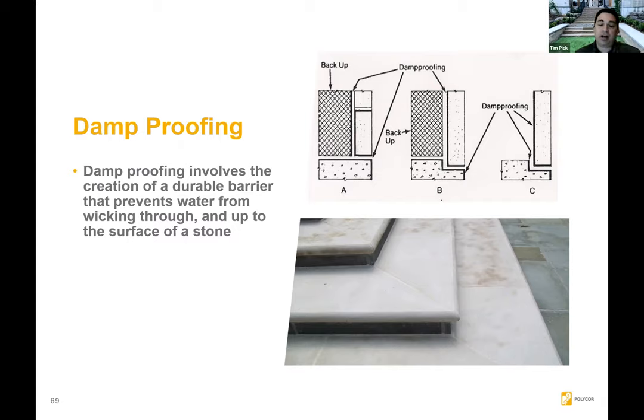If you're using a concrete slab and the slab is not cured, those alkalines and salts can come through the Indiana limestone very quickly and cause staining. So if you're using a concrete slab and don't want to do the damp proofing, you can always seal the concrete after it has been cured. But we often see concrete slabs put down and the stone put on too quickly, before the concrete has cured, and we really start to see some of the staining effect happen.